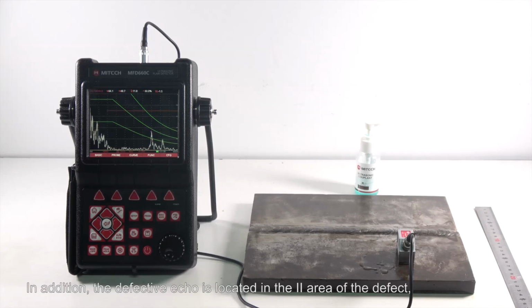In addition, for a defect whose echo is located in area two, the method to determine the defect is the same as above. For a defect whose echo is located in area one, use the absolute sensitivity line to measure the defect length, that is, in measuring S1 and S2, reduce the distance from 80% height to the evaluation line. The distance between the center of the probe and the right end of the steel plate is measured the same as the above method.